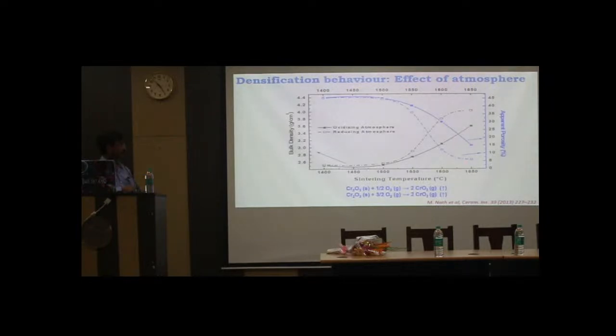Even at 1650 degrees centigrade, you see the porosity level is 15%, although it is isostatically pressed, but still the porosity level is 15%, and maybe the BD is about 3.6 to 3.8. The solid line is actually in oxidizing atmosphere, in normal furnace atmosphere when you sintered it. But why are we getting this low density?